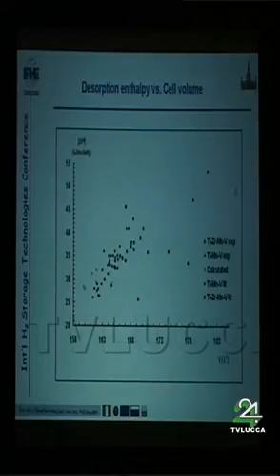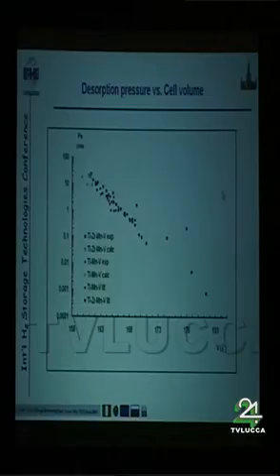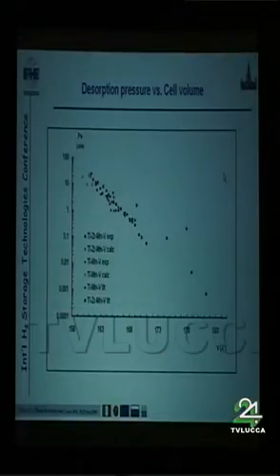In our investigations, we employed a lot of alloys, and this allowed us to find some interesting dependencies. For example, here we can see the desorption enthalpy of the reaction plotted versus cell volume of the initial alloy. We can see the tendency that the absolute value of enthalpy increases with increasing cell volume of the alloy. In the case of desorption pressure versus cell volume, the dependence is much clearer, and one can even say that it's almost linear.